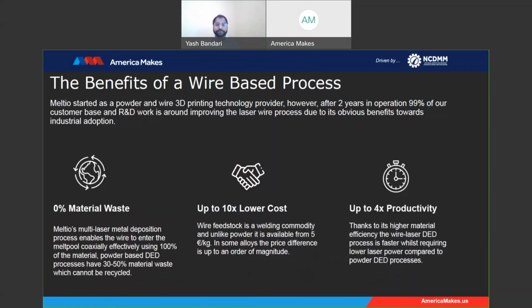Like I said, although we started as both a wire and powder technology, from the experience we are getting from customers, it's obvious that there's a lot of push for high productivity and efficiency of the process itself. So wire DED, in my understanding, is the future for printing medium to large scale components, for the sole reason that wire is the safest and cheapest feedstock in the additive market, because there is no material waste. The efficiency is literally 100% compared with powder-based processes. Especially in the powder DED process, it's only 50 to 60% efficient, and then you have problems of recycling, or you have to just trash it away.